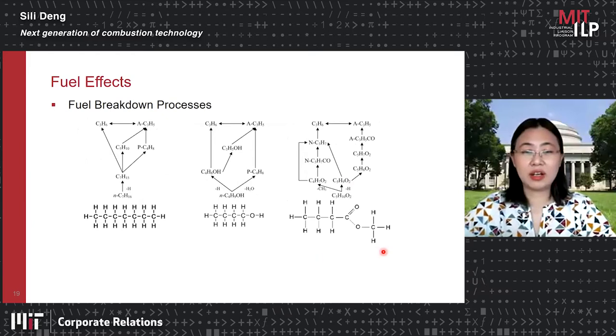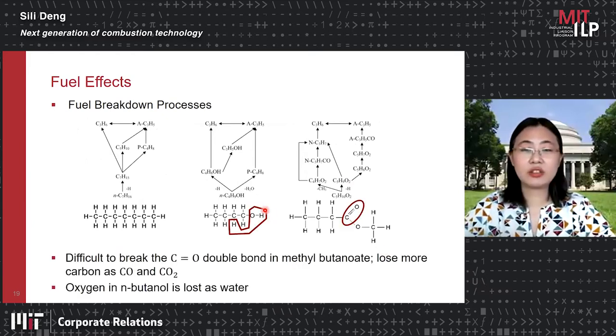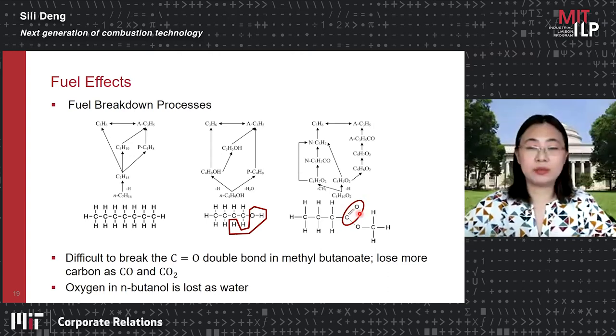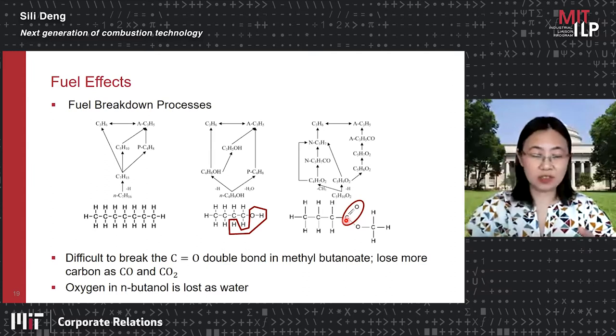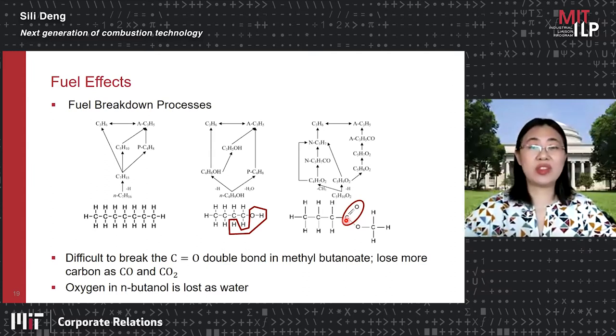To summarize here, our finding is that actually it depends on what kind of oxygen groups you have. For example, in the biodiesel, where you do see a significant reduction in the soot emission, having this C=O double bond is actually very important, such that some of the carbon will leave the system in the form of CO and CO2 without contributing to the formation of soot particles. However, for the bioalcohol, water is formed. So you are not reducing the carbon that can go into the soot. And it's merely reducing the temperature. That is why bioalcohol, in our case, is not reducing the soot emission.